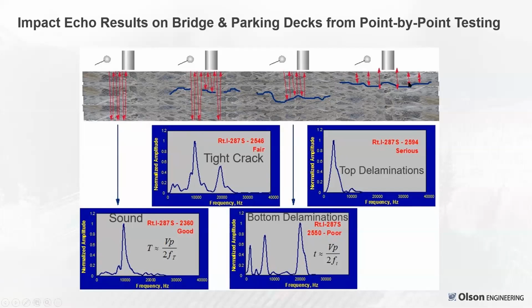What's interesting to note for impact echo is if you have a top delamination, rather than getting a thickness, once it's below about 2 inches, 2.5 inches, you're going to get what we call a flexural response, which is a very low frequency, high amplitude response. It's the hollow sound that you hear when you tap a delaminated concrete, when you're doing hammer sounding, when you hit it with a hammer. So in an impact echo result, it looks like this. It's a very high amplitude, very low frequency response. That does not indicate really thick concrete. That indicates that you have a flexural response from a shallow top delamination.